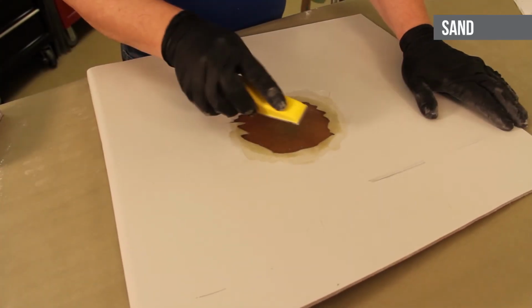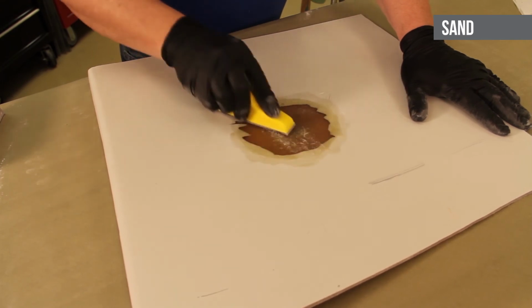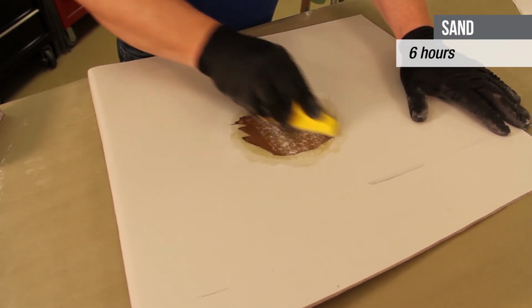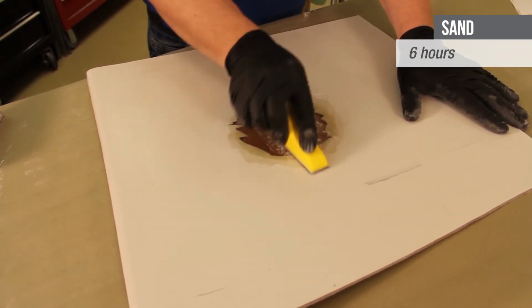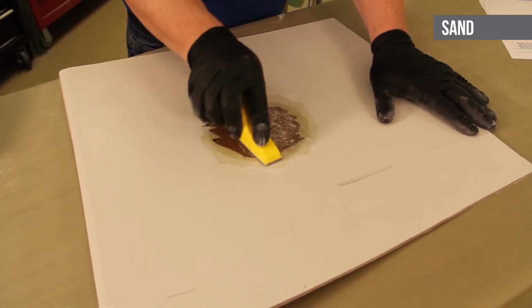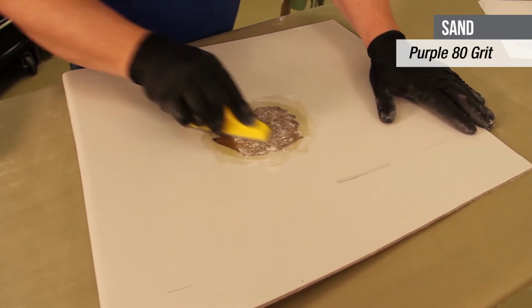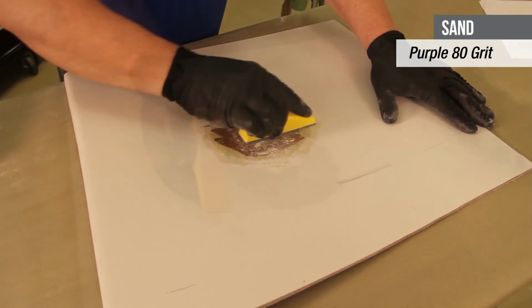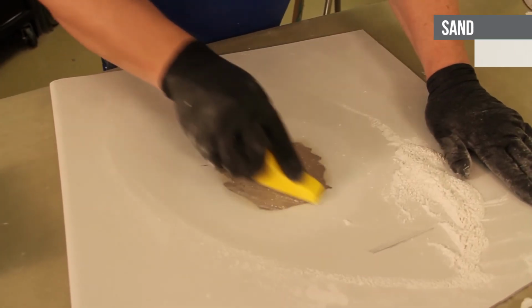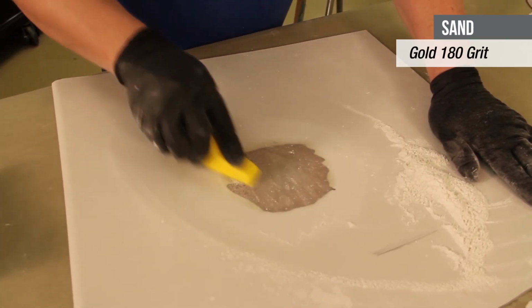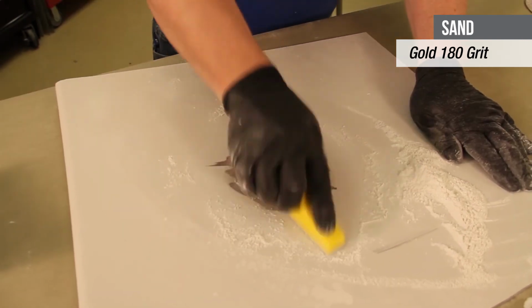Sand is the final step. Once the repair has hardened for at least 6 hours, sand down the excess resin and protruding fibers. Rough sand the repair with the purple 80 grit sandpaper. Next, sand with the gold 180 grit sandpaper to remove all the 80 grit sand scratches.